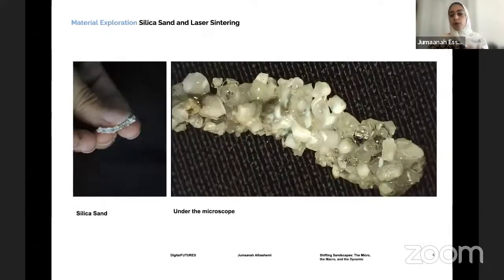And so what I really did first is really simple. I just scattered some sand onto the bed of a laser cutter, as simply put as that, and tried to sinter as much as I possibly could, very slowly and with the highest power that the machine would allow me, to try to create glass. So as you see on your right is the sand under the microscope, and on the left is it in its real scale.